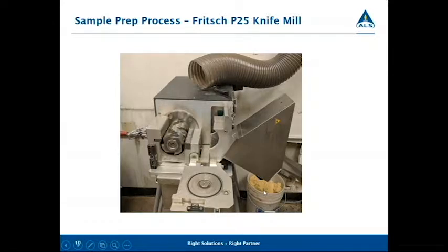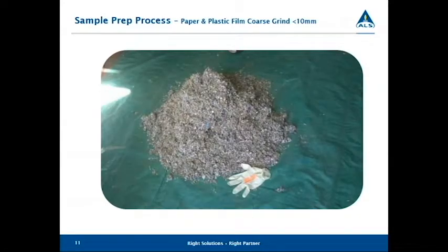So what we'll do is we'll take the samples, and if they're large pieces, we'll have to pre-cut them by hand, or sometimes we'll run them through a hammer mill. Samples that have plastic in them, we pre-freeze those with liquid nitrogen, and a lot of times we'll run those through a hammer mill to get the material reduced in size to about 10 millimeter.